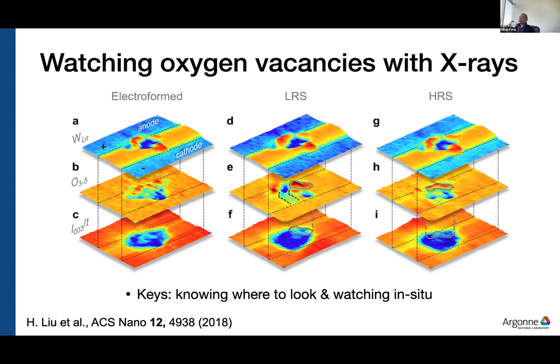On the left, I'm showing the electroformed conducting filament in a tungsten oxide epitaxial film. The top shows the tungsten fluorescence, the middle panel shows the oxygen concentration, and the bottom shows the Bragg peak intensity. You can see that as we form this conducting filament, it's creating a lot of havoc in that material. It's basically making it amorphous and displacing the tungsten all over.